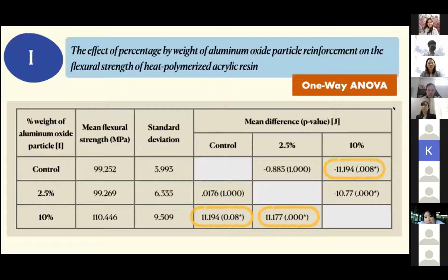One-way ANOVA determines that there was a significant difference between groups, and post hoc Tukey indicates that the 10% by weight group was significantly higher than other groups.